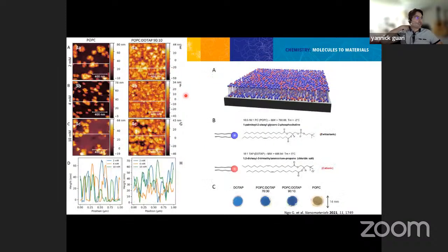We can also grow Prussian blue nanoparticles on a glass slide covered with a lipid bilayer. Depending on the lipid bilayer composition and the concentration of reactants, as you can see on this AFM image, the coverage density can be modified. The presence of a cationic charge in the lipid bilayer favors the coverage density. As in the previous case with the amine, favoring the interaction between the surface and the Prussian blue precursors is the key to obtaining a high coverage.